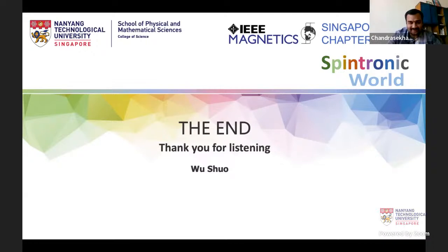Any other questions? Vishu, along similar lines, I would like to ask, your chamber, for sure you have MgO there. So why didn't you observe the similar effect with magnesium oxide? Why didn't you see this cobalt oxide hybridization with MgO? If you could have tried with MgO cap. With MgO capping, we also have this cobalt oxidation induced SOT enhancement, but compared with MgO capping, we observe the HFO capping can stabilize the PMA better, which is really strong PMA.